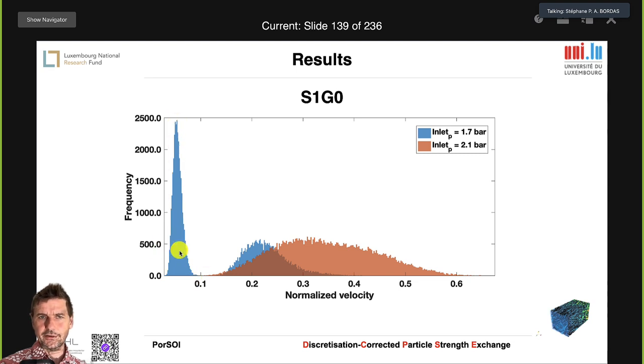Okay, a lot of points in the domain have low velocities. And you have here this little bell-shaped curve, which gives you an idea that you have an average velocity of about 0.25 in this little distribution. And if you now take a much larger pressure, 2.1 bar, then you can see that these low velocities don't appear because they are all higher.